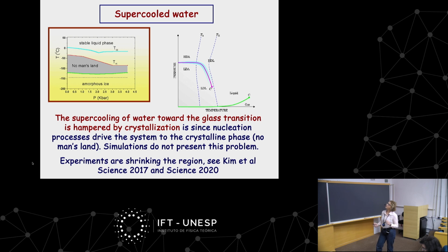And then by heating, we can arrive at a supercooled liquid here again, but still we have a limit at which it turns to crystal. But in this region here, since many years, experimentalists have seen that there are two kinds of amorphous phase, a high-density amorphous and a low-density amorphous. So here is the reverted phase diagram.